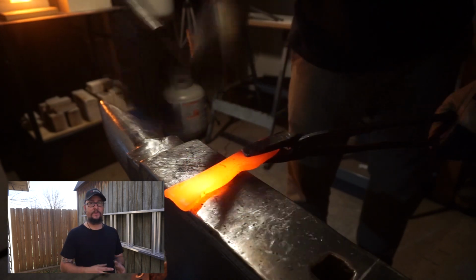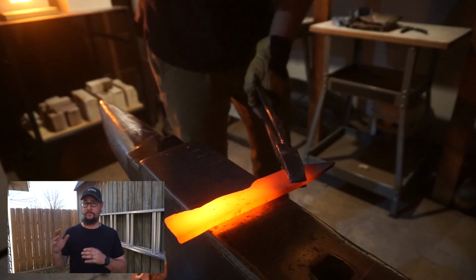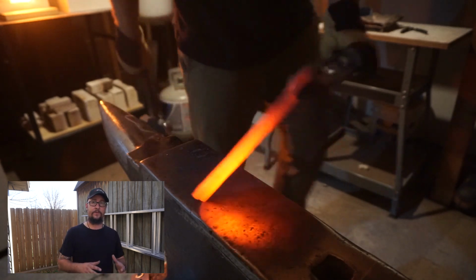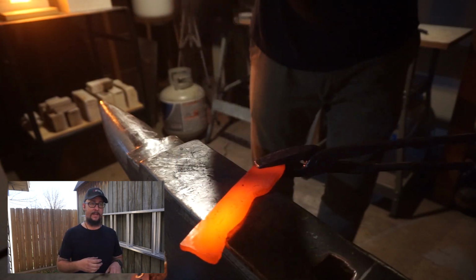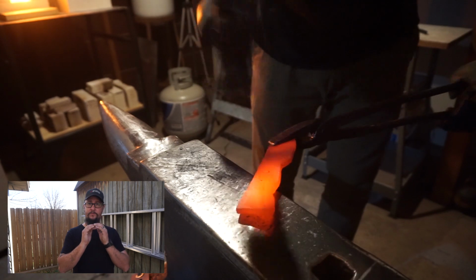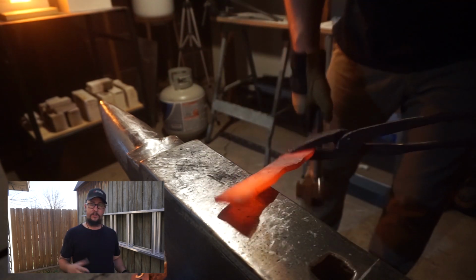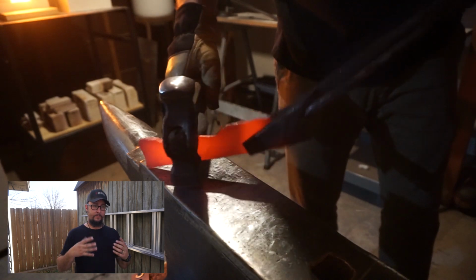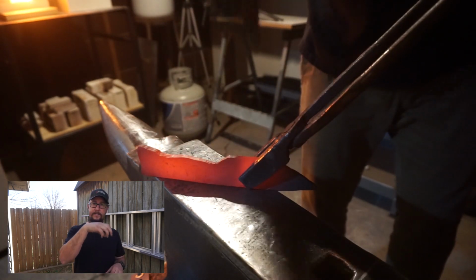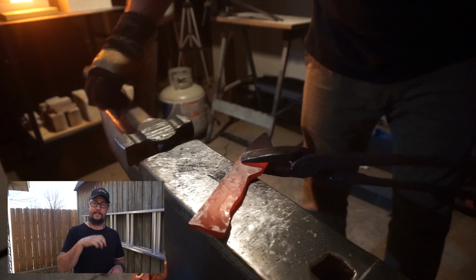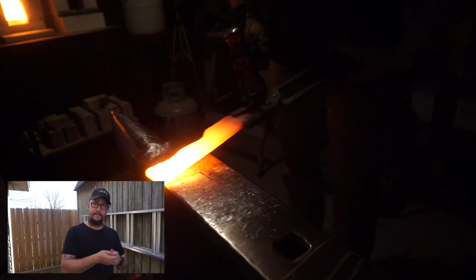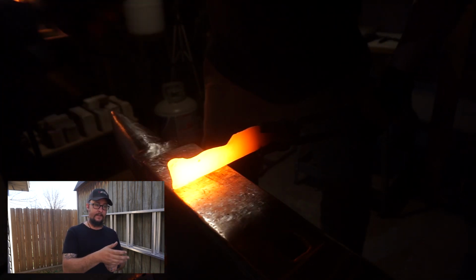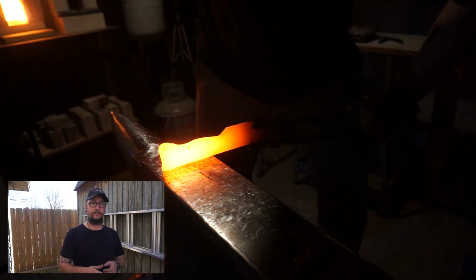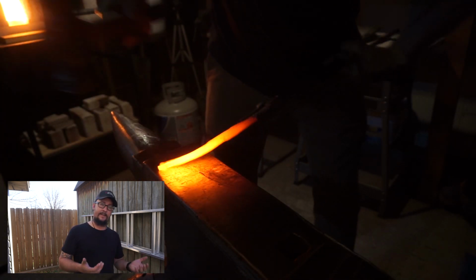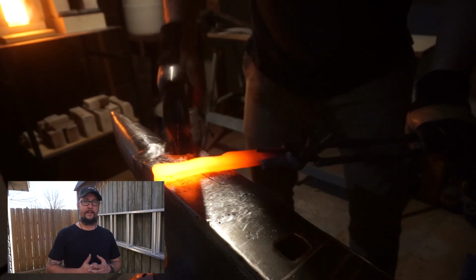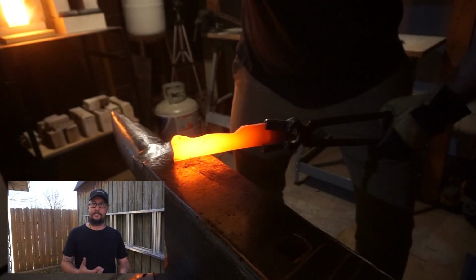That is a lot easier with a heat treating oven than it is with the forge. You can do it in a forge, but you're risking a little bit. If you put something like a baffle in your forge, like I do with that piece of angle iron, you could also use square tubing if you want to, that way the flame is not directly blowing on the actual steel itself, and you can kind of modulate where you're at and make sure you keep that consistent temperature for as close to 10 minutes as you can. It requires a lot of work, but it's a tricky steel to use.